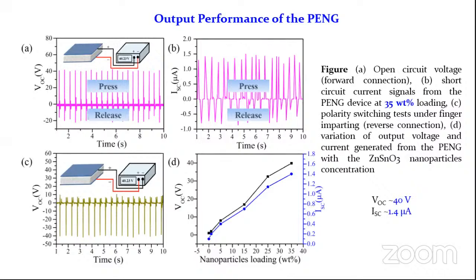To know the effect of nanoparticle loading on the output voltage, we fabricated several devices with different nanoparticle loadings. We found that at 35 wt% loading, we got the maximum output voltage. Actually, when we add nanoparticles, we are adding dipoles in the nanocomposite. So on increasing the nanoparticle loading, the number of dipoles in the composite increases. Because of that, the output voltage increases.